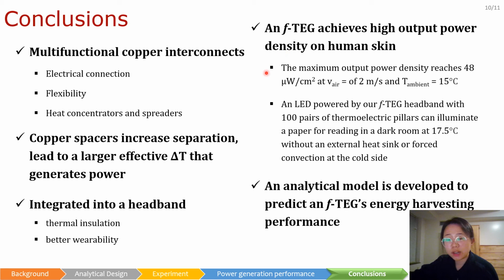We have demonstrated a flexible thermoelectric generator that achieves the highest reported output power density on human skin. The maximum output power density we measured was 48 microwatt per square centimeter at a wind speed of 2 meters per second and ambient temperature at 15 degrees C. The device is capable of powering a commercial LED to illuminate a paper for reading in a dark room at a room temperature of 17.5 degrees C without an external heatsink or forced convection at the cold side.